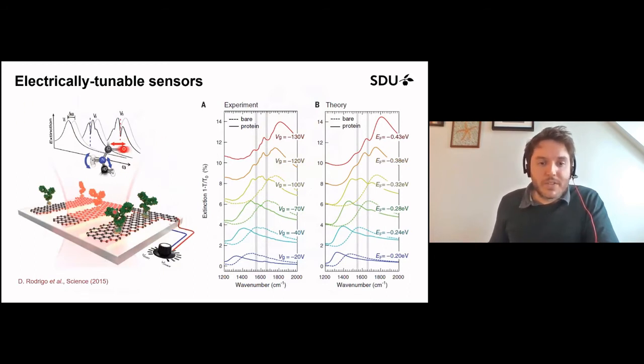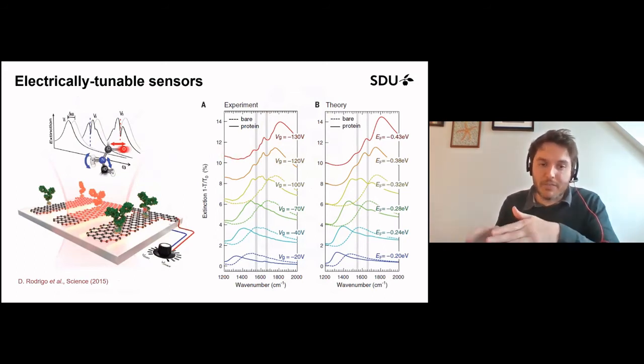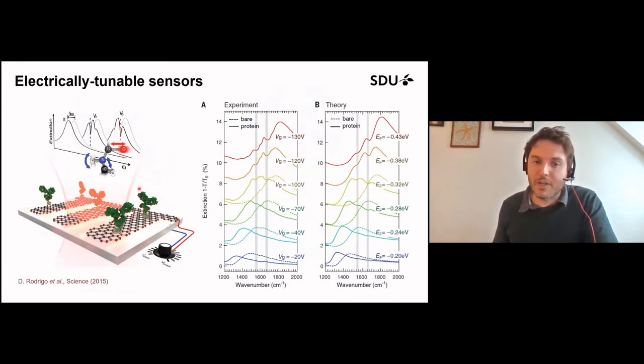We can also use this in terms of biological sensing. So we have these graphene plasmon resonances that can themselves be influenced by the optical properties of an analyte molecule. It might have an optical resonance of its own. And this interaction of the two resonances can effectively tell you something about the particle that you might want to detect, right? At these particular frequencies, for example, you might have a specific signature of that molecule, and then you're able to detect it by sweeping the graphene plasmon resonance.